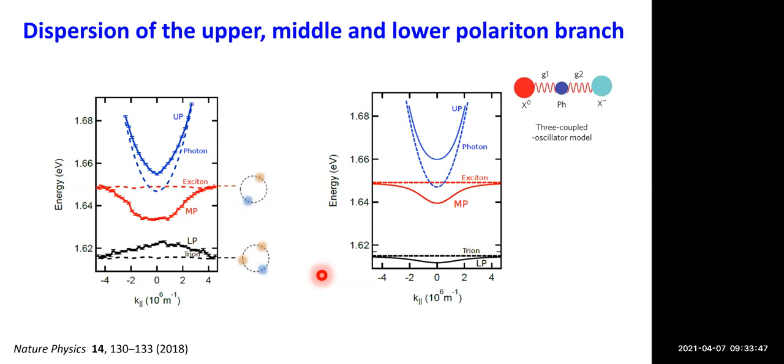And so we are still in the lower regime of doping, and that is what we think overwhelms this cavity trion interaction and causes this kind of level attraction. What we think is happening here is that an electron is being delocalized between the trion branch and the exciton branch because of the low density regime that we are working in. Of course, you can tune this further if you use some kind of electrostatic doping device where you can continuously tune the free electrons in the system in and out. What we expect is that this behavior should be reversed, but that is not something we could do with this particular sample, because this is a fixed device with a fixed concentration of electrons.